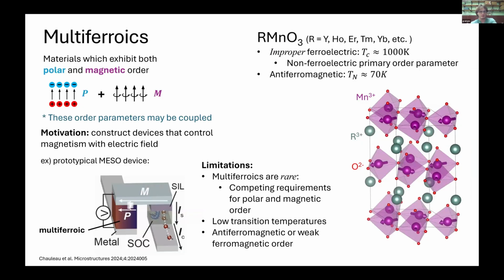So a multiferroic, if you're not familiar, is a material where you have both polar and magnetic order. Ideally something that is both ferroelectric and ferromagnetic. A ferroelectric is just like a ferromagnet, but for the electric polarization. The exciting thing about these materials is that these two order parameters may be coupled. So you could, in principle, construct a device where you control the magnetization with electric field.